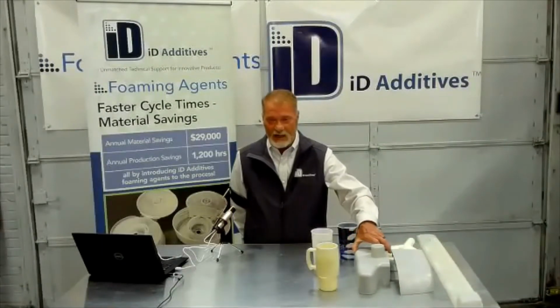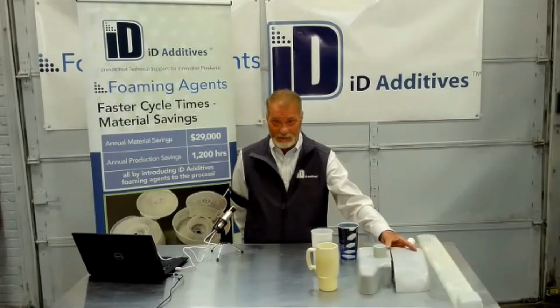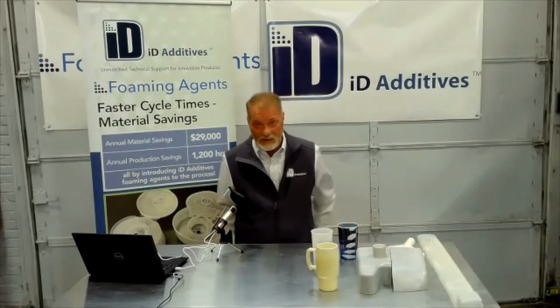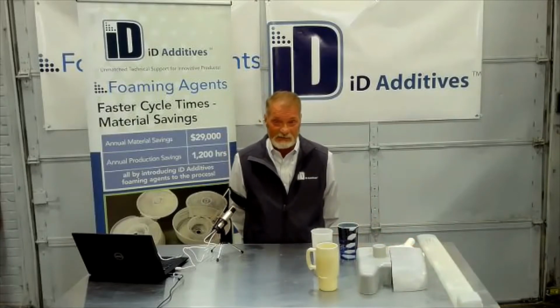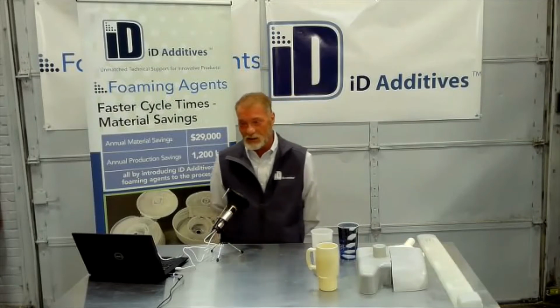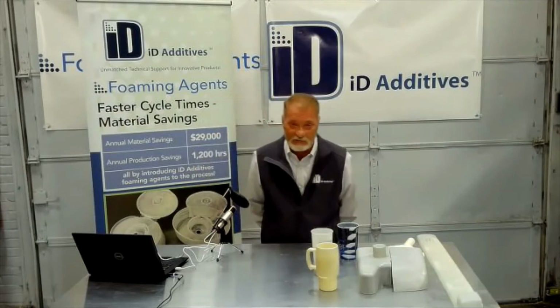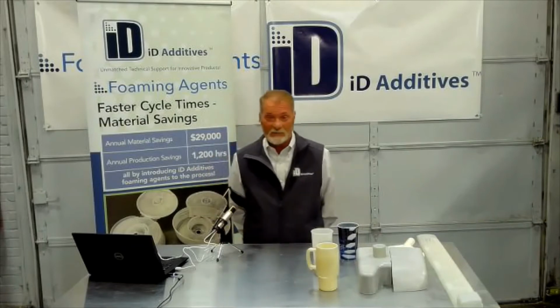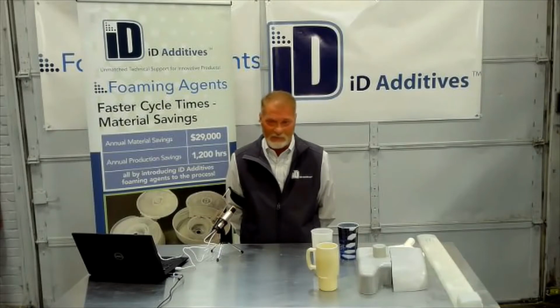A little bit goes a long way. I have foamed a lot of polycarb and a lot of glass-filled nylon. Nylon 6, nylon 6.6, up to, I think, 30% glass-filled. Actually, I'm going to do a trial tomorrow on a 20% glass-filled nylon, just to help push out some sink. So I'm excited about that. The nylon foams really work. I don't see any issues with nylon.